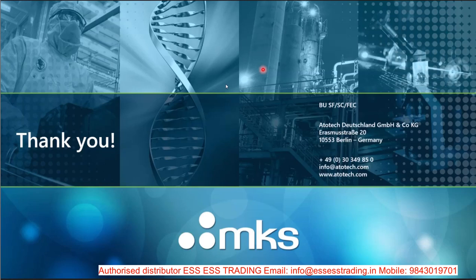Thank you, Britta. Let's continue with the next one. Can this chemistry achieve a thickness higher than 3 micrometers? It's still an immersion tin process, so the thickness is somewhat limited. If you take the time, it's possible. We have an immersion process, for example, that we applied for QFN as well, where we can achieve 3 micron, but it really takes a long time. It's a replacement reaction, so you also dissolve a lot of copper. There is also an autocatalytic process in development, so depending on the target application, maybe you can reach out to me later by mail and we can discuss.